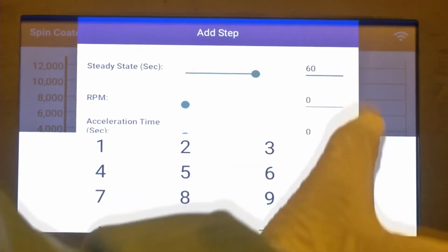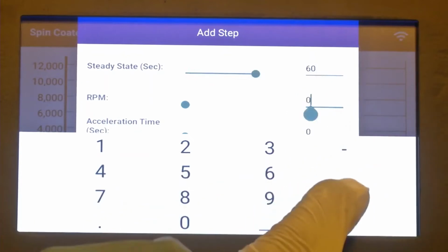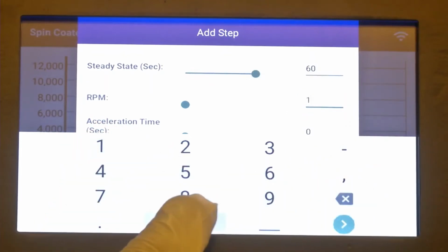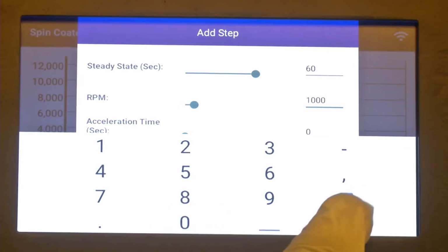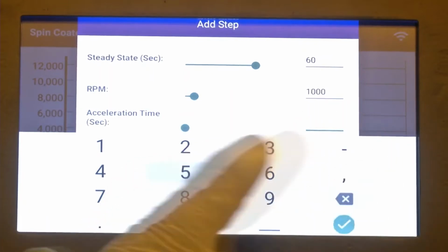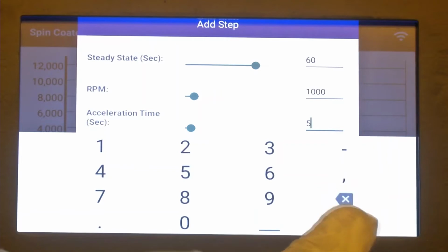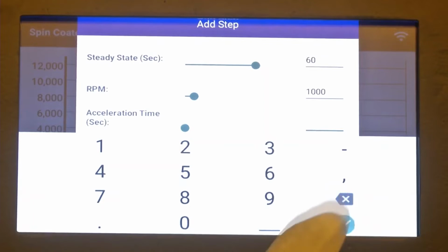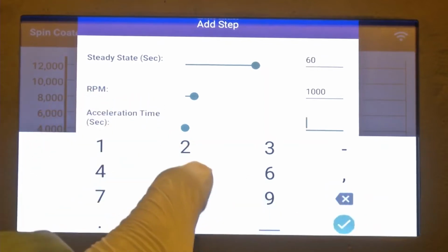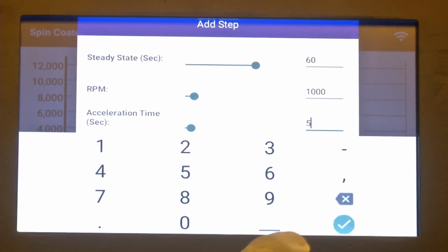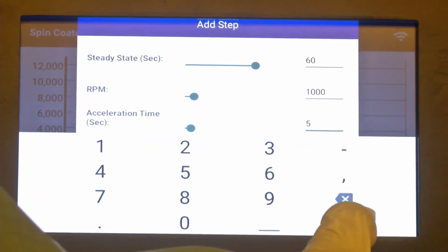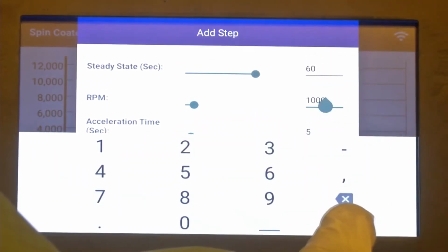Generally for photoresist we give 4000 RPM for 40 seconds, but in this case we have optimized to get a flexible substrate, so we are giving it for 60 seconds. The RPM is around 1000 and the acceleration will remain almost the same, which is around 400. As we had discussed, acceleration speed, but in some spin coaters acceleration time is there, so you can do the math and calculate the acceleration time. For this we have calculated it to be 5.